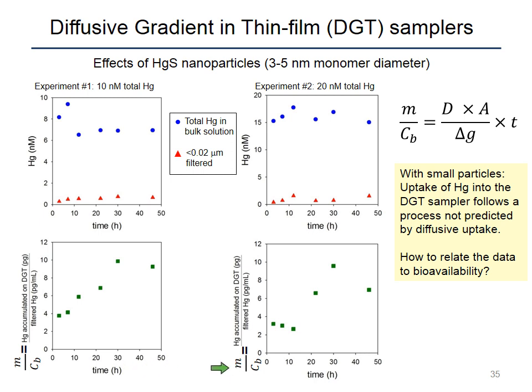Basically, the take-home here is that the uptake on these samplers, if it really was just taking up dissolved mercury, should be a linear trend. But we don't have a linear trend here, at least not one that is reproducible. And what's happening here is that the nanoparticles are somehow interfering with the uptake rate of the dissolved mercury on these samplers.